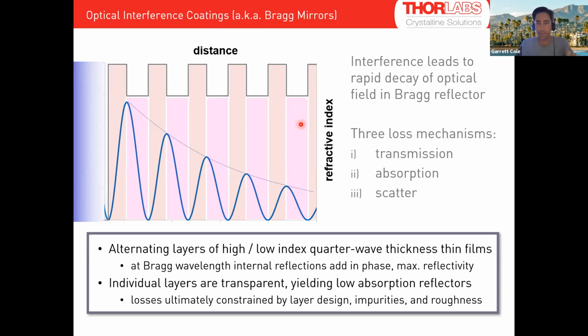So again, it's something you're going to design in, and then you'll have these two excess loss parameters, the absorption and scatter. They're pretty obvious given the name. I'll go into more detail a little bit later, but the basic idea: absorption is when you have either defect states or you're illuminating above band gap or some sort of process that gives you absorption of photons into the structure, and scatter is going to be due to some imperfect surface, right? You have a wavefront error, or you have micro roughness, or you have interfacial roughness that scatters photons off axis or off the direction that you want.